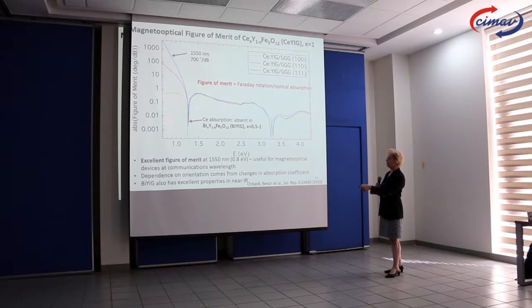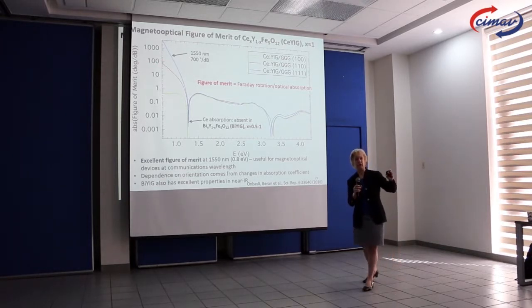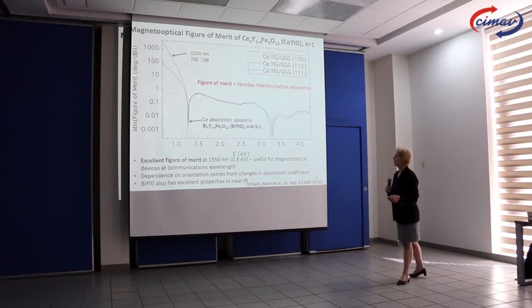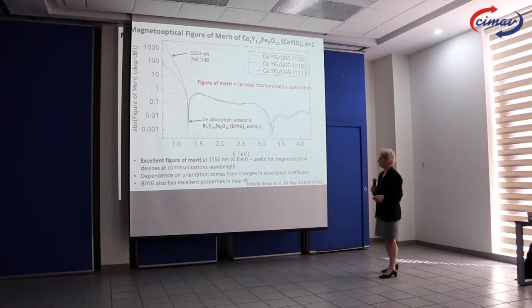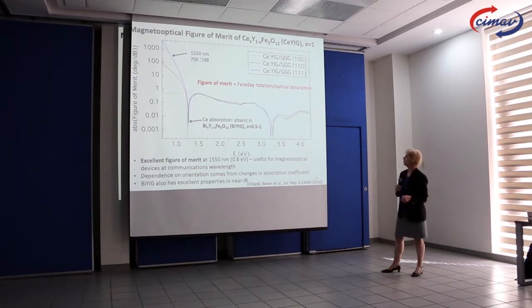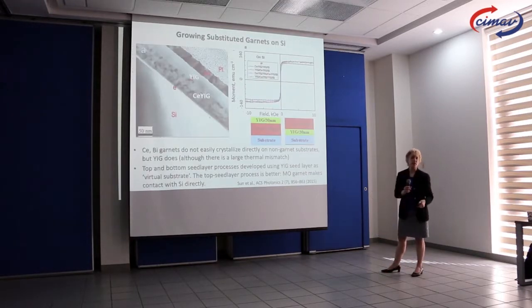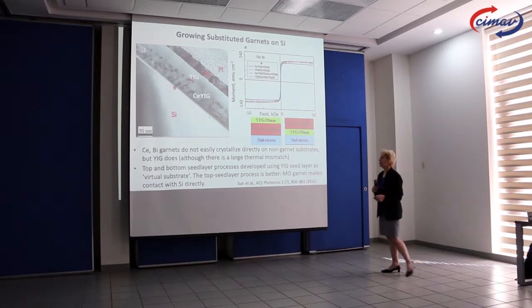This is the near infrared, this end of the plot. And you can see the figure of merit, degrees per decibel. So how many degrees of rotation per decibel of loss? It can be hundreds. So we have very low absorption in these materials. So this is a good thing to start with. And now we have to grow it onto a device, grow it onto chips.